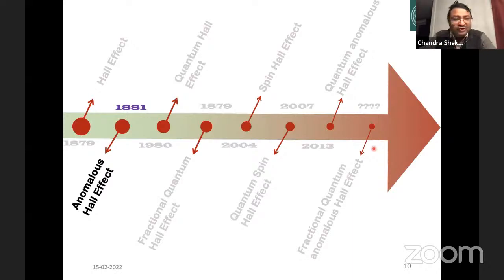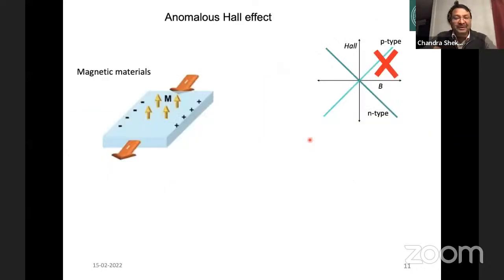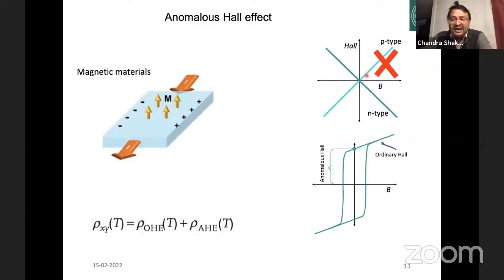So I'm going to show another effect, which is called the anomalous Hall effect. The anomalous Hall effect was basically discovered 2 years after the basic Hall effect. So what will happen? We have two types of material, I said, magnetic and non-magnetic. When we measure the same property, same voltage, same resistance in a magnetic material, this voltage is no more linear. It will change the behavior of this measurement. This measurement looks like a non-linear behavior, not a linear behavior.